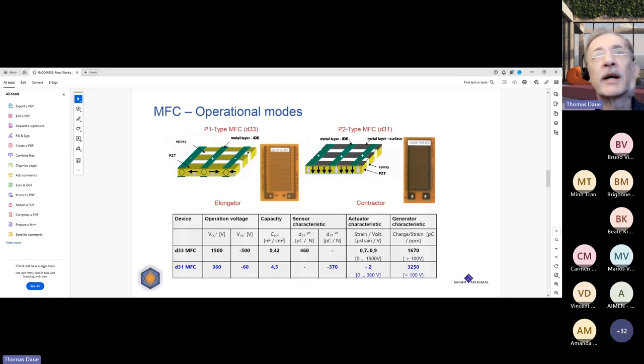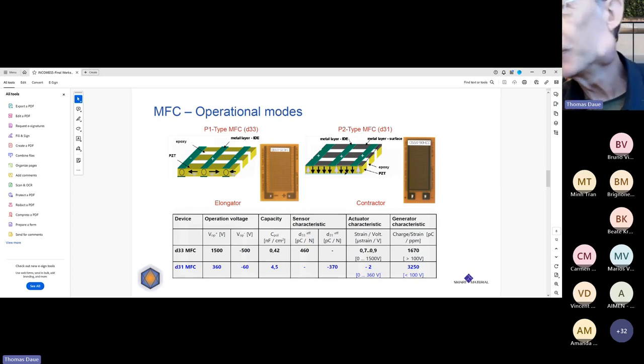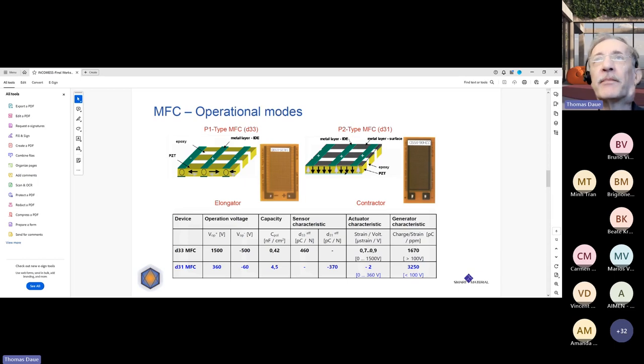So I just want to put this slide up for all of you who might not have the different operational modes in mind. The D33 mode, which is a PZT mode along the long direction of the PZT, has interdigitated electrodes and basically is energizing the PZT in the planar mode here. It has a much higher strain component than the D31, but it is also very high impedance. The D31 or the P2 type, which we use for the energy harvesting, has an extra metal layer in there, a similar build-up with the electrode, but in principle, it is energized in the thickness direction, what you normally know from PZT wafers or similar.